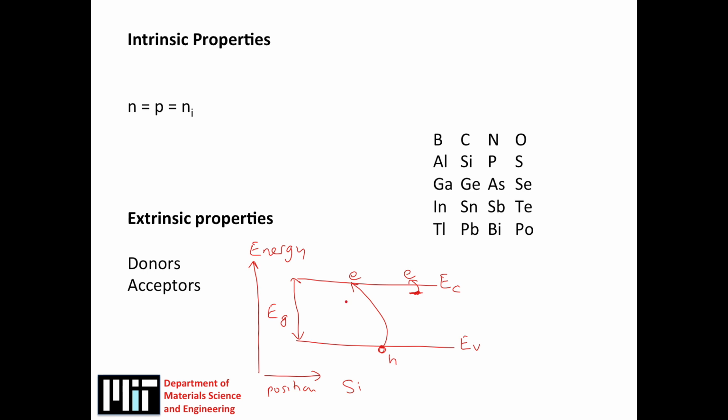So the movement of the electron from this little level here, which is associated with the phosphorus atom, into the conduction band, which is global across the material, allows conductivity to take place, because the electron sitting here had nowhere to go, but once it's up in the conduction band, it's really a free carrier and it can go from one side of the material to the other.